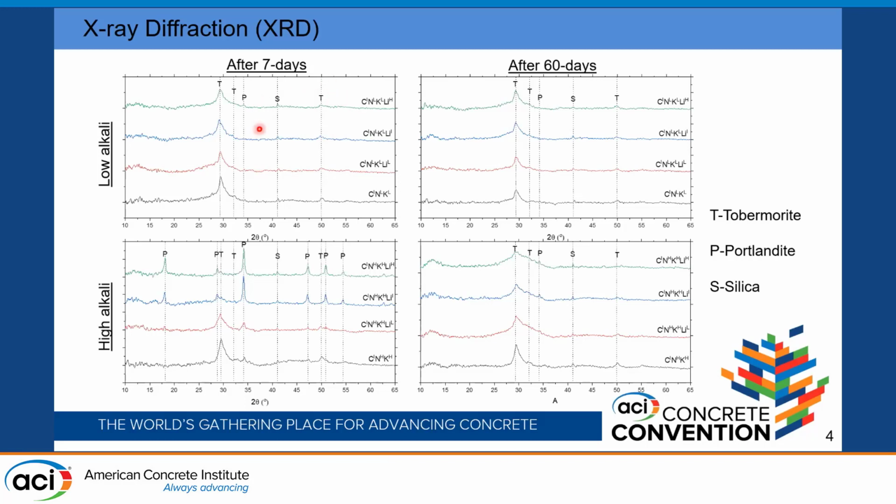From the study, we can see that adding lithium to the low alkali groups really does not have much effect, and there is no new phase formation even after 60 days. Most of the products are formed after 7 days, and they remain the same even after 60 days.